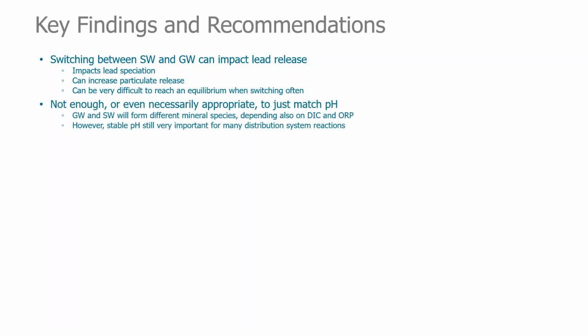It's not enough or even necessarily appropriate to just try to match pH. Groundwaters and surface waters will form different mineral species depending on DIC and ORP, so it's not just about pH. Now, of course, stable pH is very important for many distribution system reactions, and it should be a goal within a certain supply area, a certain zone to maintain as stable a pH as possible. But for corrosion scales, we have to think about more than just pH.